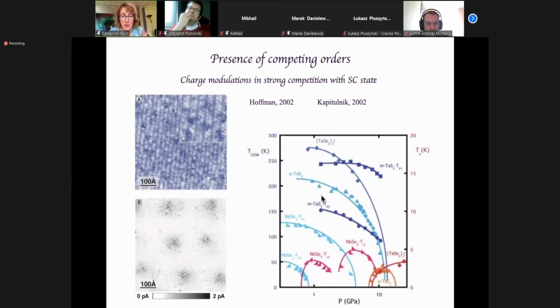In niobium diselenide, we see the charge orders in blue and superconducting orders in red. The difference with cuprates, as you will see shortly, is that there is a factor of 5 between the charge order and the superconducting order. In cuprates, they will be of much the same order of magnitude.